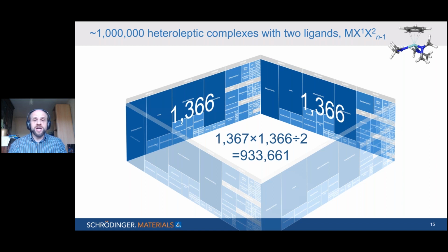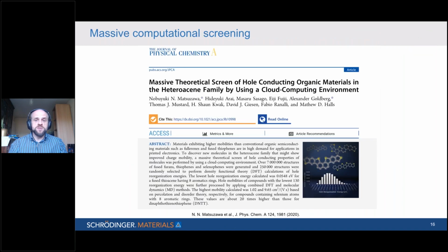this really does provide a challenge for computational modeling and screening. I highlight here a recent paper, not in the area of precursors, but in the area of organic materials for displays, where my colleagues did 250,000 DFT calculations. So this was really a huge computational effort. That's probably what we can think of as the forefront of state of the art nowadays in DFT.